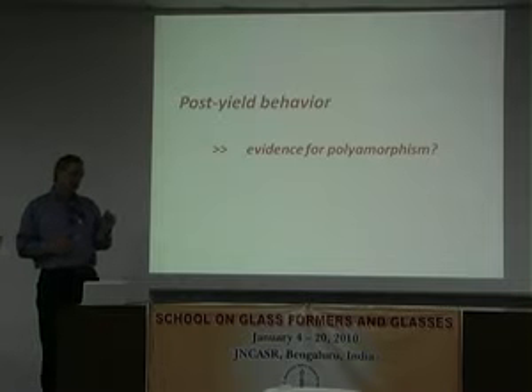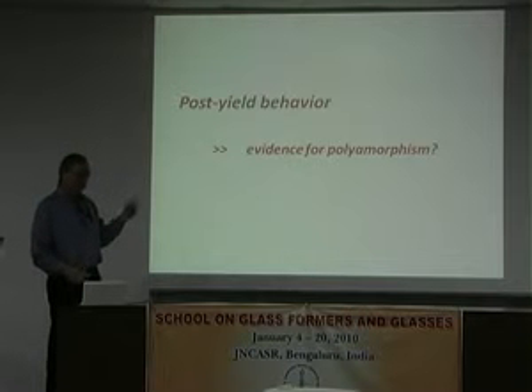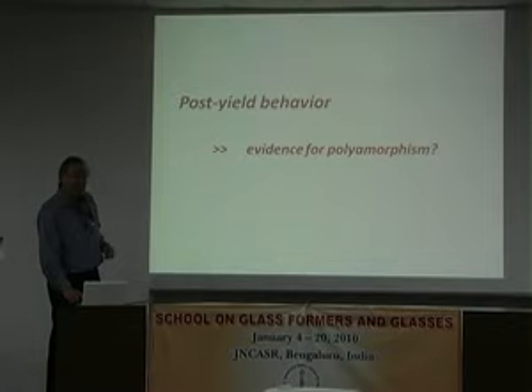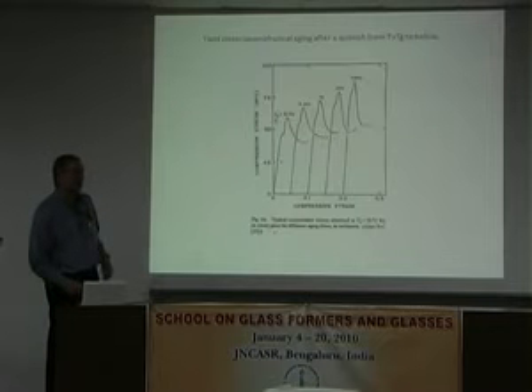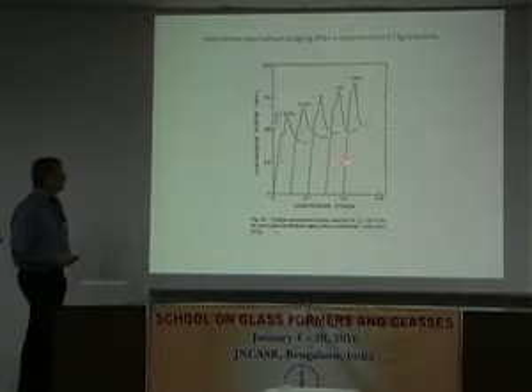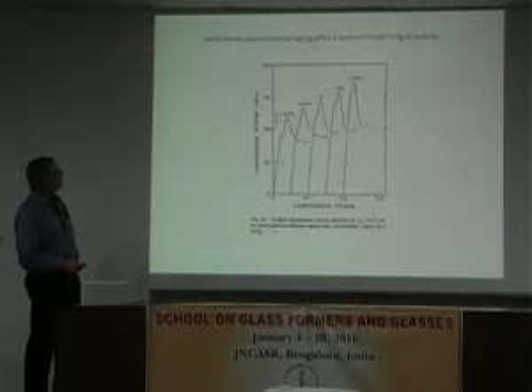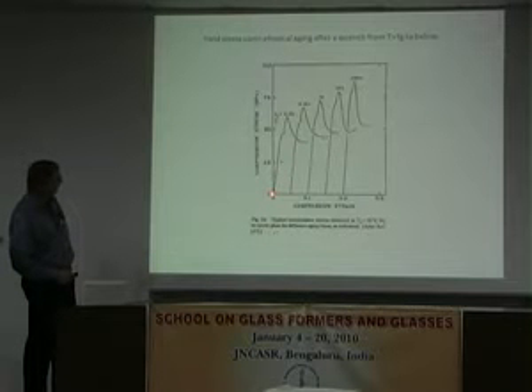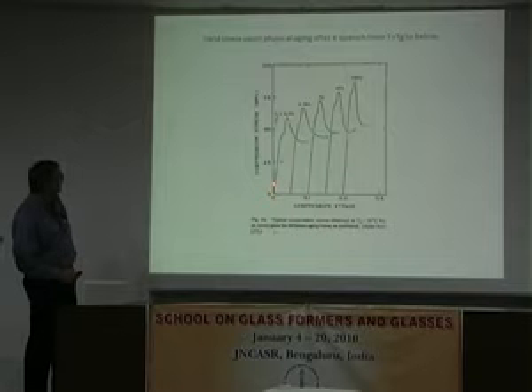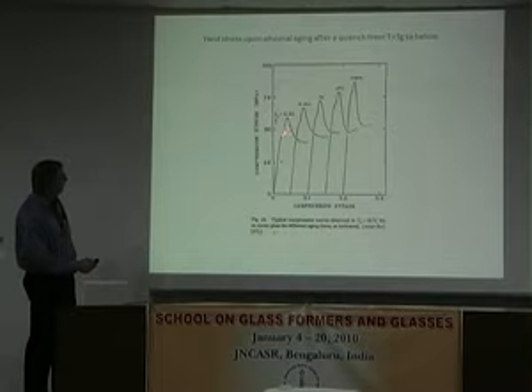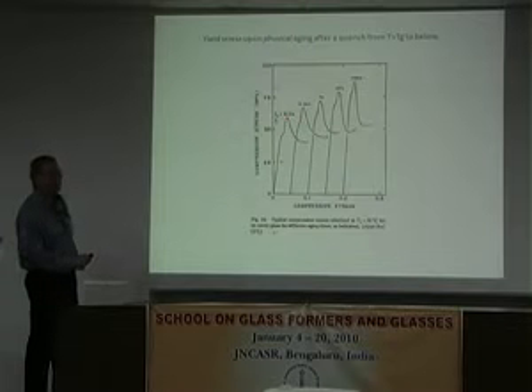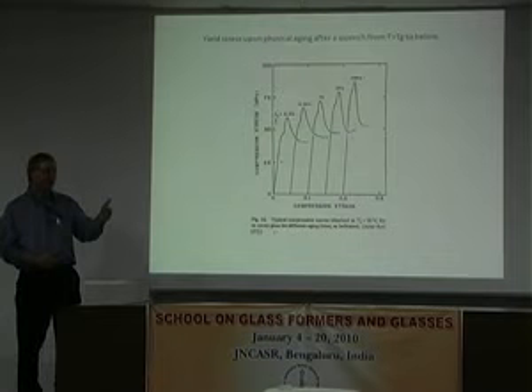Yield means what? Okay, so I'm going to show you a picture of yield. Here's a picture of yield. Okay, so this is some experiments, again, on the same old epoxy we like to work with. And this is some work I did with Christian Gazelle in Nancy in France. And here's the experiment. You're going to run up at a low rate, and when the sample gets to yield, then he increases the rate so he can get 2 data points out of one test. Okay, that's the reason for that.